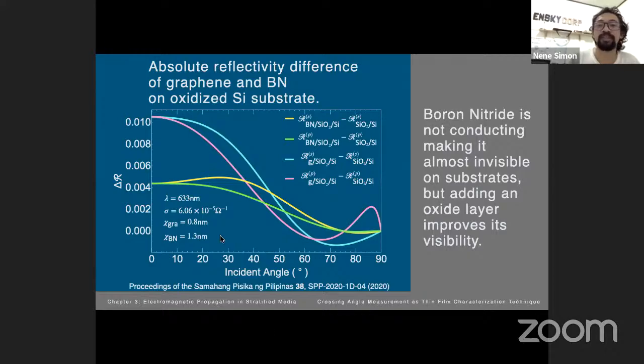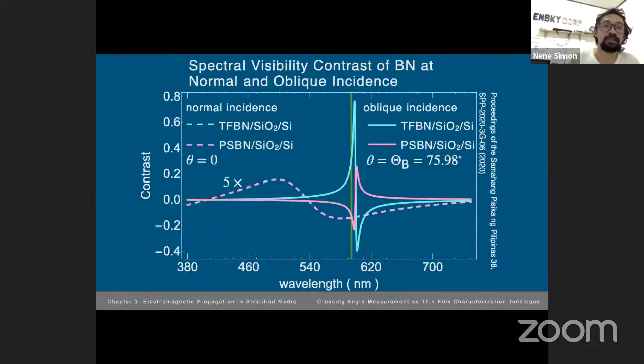In this plot, the 2D materials are modeled as perfect sheets. And I'd like to take note that boron nitride is not conducting, making it almost invisible on substrates. But adding an oxide layer improves its visibility, as shown here. So our calculation shows that the visibility of boron nitride is improved when the incident light shines onto the sample at the substrate's pseudo-Brewster angle.